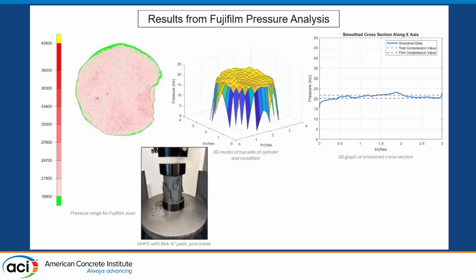And so the pad showed a uniform distribution across the surface, which was very interesting. On the right-hand side, you can see a cross-section that was taken from the point map on the film scan. The red dashed line is the value that we derived from testing, so around 21 KSI. The blue dashed line is the value given from the Fujifilm program, which was the average of all the data points in that film scan, around 20 KSI. So the Fujifilm proved to be a very accurate representation when it was within the pressure scale range.